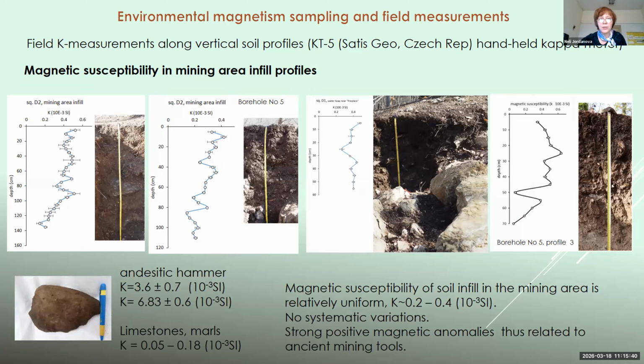And these first examples, which you see, are susceptibility variations in infill profiles at the mining area where the ore was extracted. So susceptibility variations are not systematic, they just reflect the deposition of the soil infill after the abandonment of the mine. And of course, limestones and marls show very low magnetic susceptibility in contrast to andesitic hammers, which display much stronger magnetic susceptibility. So these initial measurements showed that strong positive magnetic anomalies are probably related to the presence of ancient mining tools at the site.